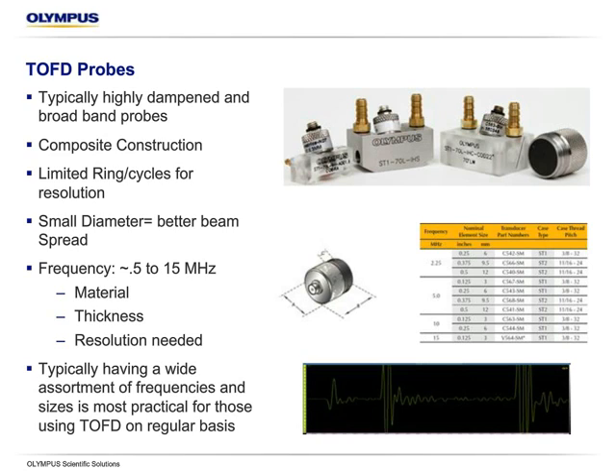Smaller diameter is going to give us a better beam spread, so more volumetric coverage. So we typically use very small elements, 3 millimeter, 6 millimeter crystals inside the probe to give us that better beam spread. Typical range of frequencies are about 0.5 megahertz to 15 megahertz, and they can go lower and higher, but typical industrial applications are right in there. It can depend on the material, the thickness, the resolution needed. Anybody that does TOFD on a regular basis is wanting to have a whole collection of different probes, frequencies, sizes, because the individual parameters of the probe is going to make a big difference in the resolution you make with TOFD.